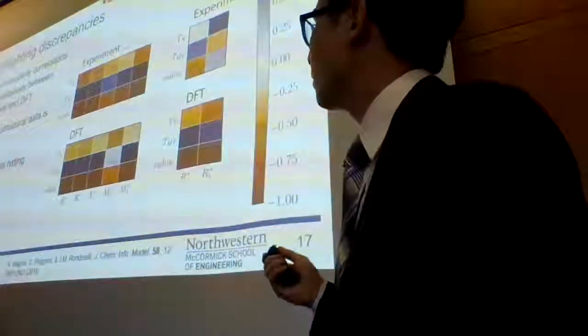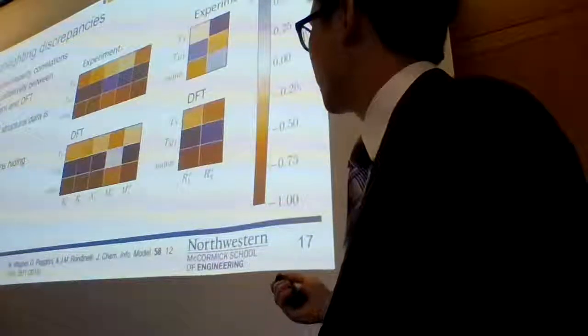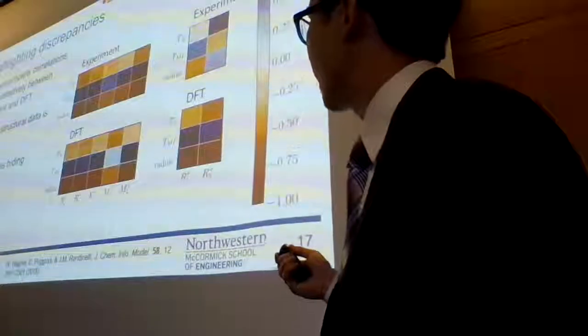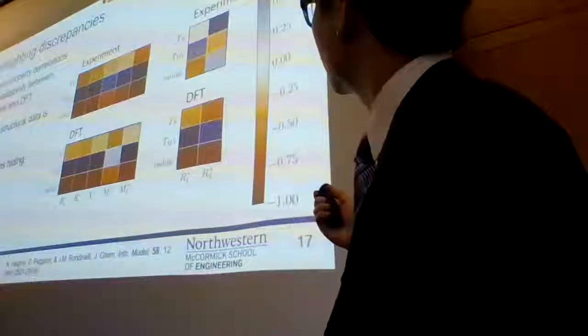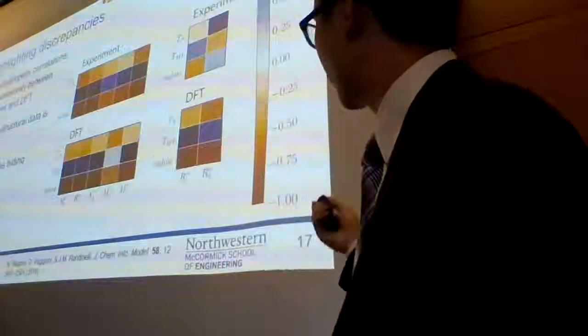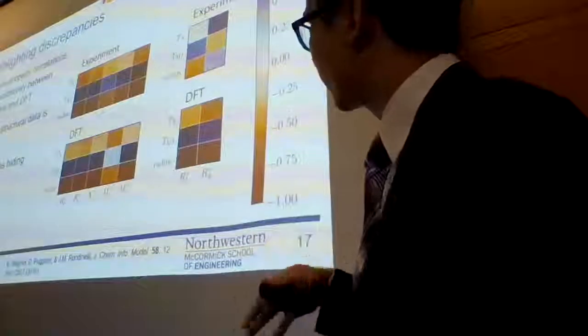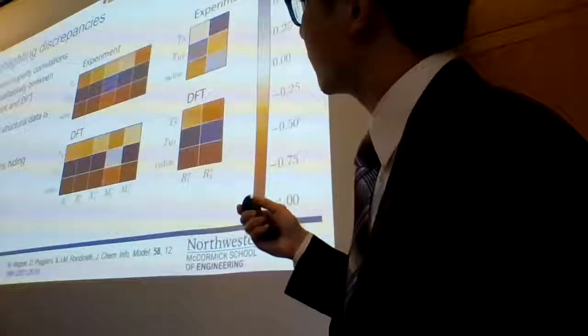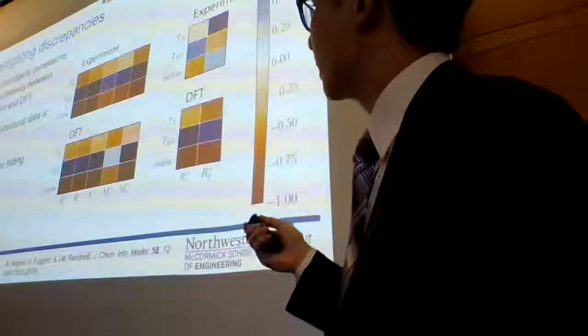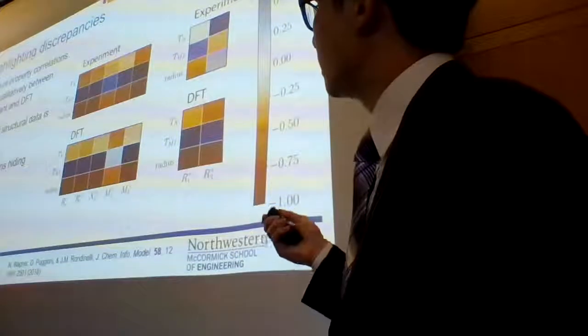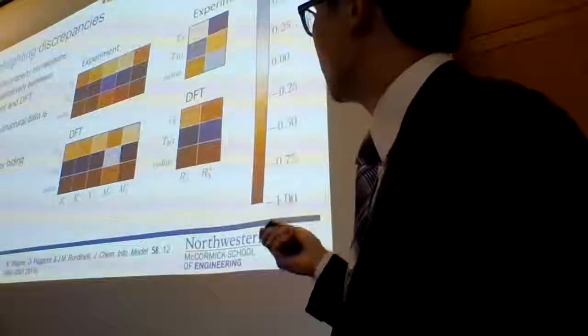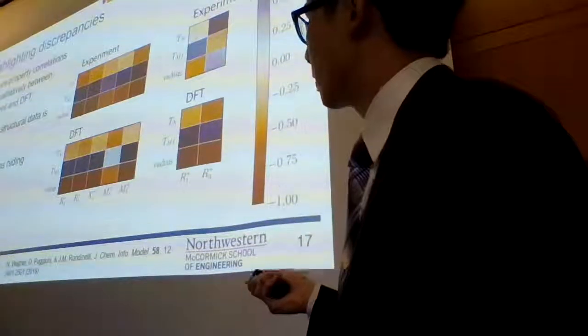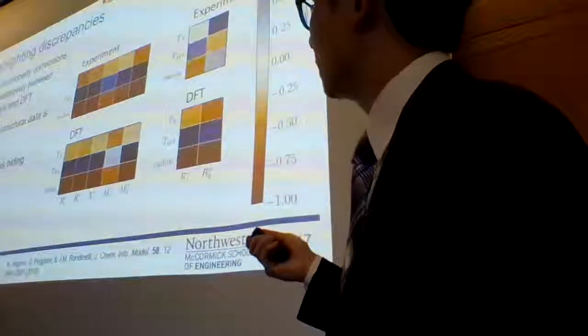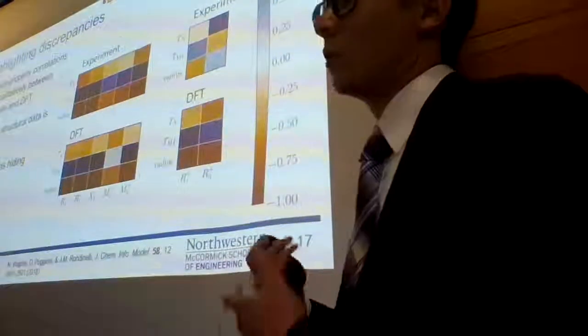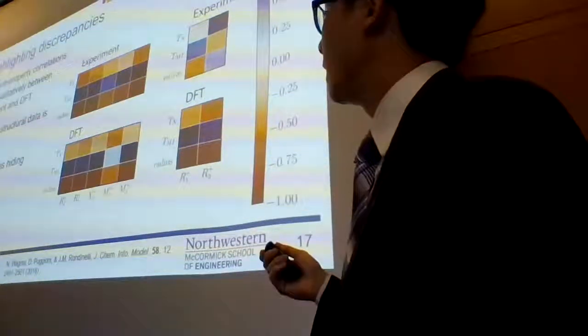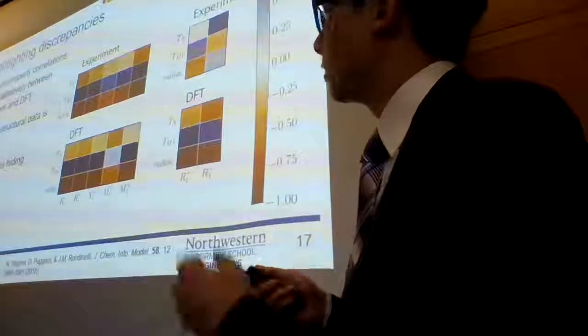The most simple thing you could think of doing is plotting the correlation between a given mode and some ordering temperature. This is the magnetic ordering temperature, and this is the metal insulator transition. A purple square indicates a high degree of positive correlation, and a dark orange indicates a high degree of negative correlation. Between structures that are reported in the Inorganic Crystal Structure Database, so experimental reports, you see this monotonic correlation with these other modes, which are associated with the cubic to orthorhombic distortion, which makes sense. Essentially, the larger the radius of the cation, the smaller the overall distortions are. And so you see one direction in terms of whether the transition temperature is going up or down.